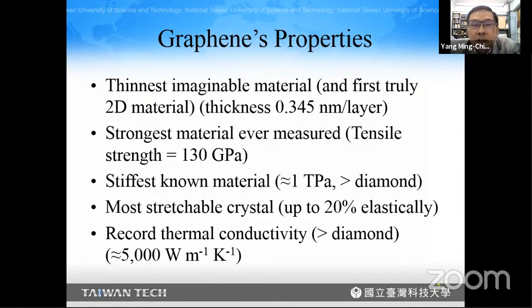Now about graphene's properties. Graphene is the thinnest imaginable material, and of course the first truly two-dimensional material, with a thickness of around 0.345 nanometer per layer, which is a single layer of carbon. It is the strongest material ever measured, with a tensile strength of around 130 gigapascal. It is also the stiffest known material, with a Young's modulus around 1 terapascal, greater than diamond. And it is also the most stretchable crystal, up to 20% elasticity.